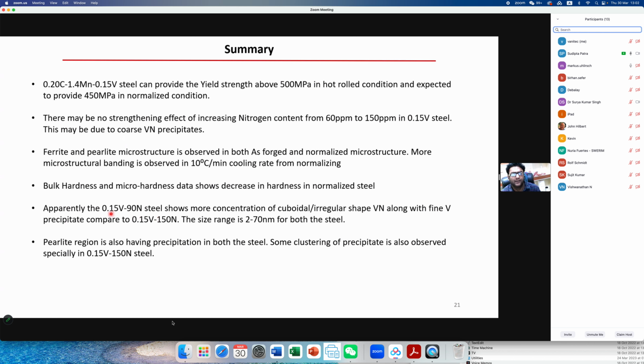Apparently, the 0.15 V steel shows more concentration of cuboidal and irregular vanadium precipitate, along with fine vanadium precipitate, compared to the 0.10 V steel, but we need to see more replicas to confirm. Though it is not expected from the literature, we observe only that. The pearlite region is also having some precipitation in both the steels. Some clustering of precipitate is also observed, which may be due to the high temperature precipitation in this high vanadium, high nitrogen steel.